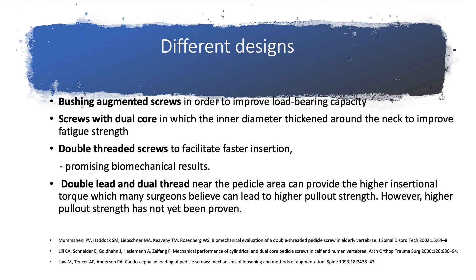There are various designs available for pedicle screw-based systems today. There are bushing-augmented screws to improve load-bearing capacity. Screws with dual core diameter have a thickened inner diameter around the neck to improve fatigue strength. Double-threaded screws facilitate faster insertion. Double lead and dual thread near the pedicle area can provide higher insertional torque, which many surgeons believe leads to higher pull-out strength — however, this has not yet been proven in biomechanical studies.